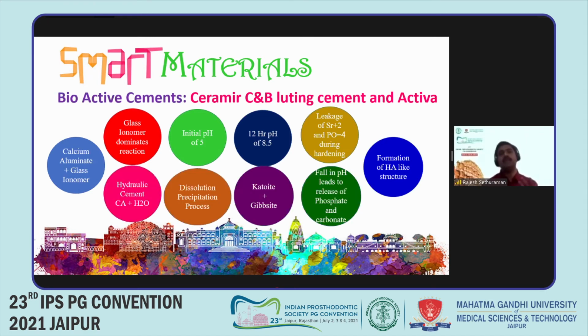On the other hand, we have the calcium aluminate, which is already present in it, which reacts with water and forms a dissolution and precipitation reaction, which ultimately results in two components, katoite and gibbsite. Both of them result in a rise in the pH, so the pH becomes as high as possible. Whenever there is a fall in the pH, that is, whenever there is an acid attack and the critical level of 5.5 is breached, there is release of phosphate and carbonate, which together with the leakage of strontium and phosphate from the glass ionomer component results in the formation of a hydroxyapatite-like crystal. Believe me, Ceramir C&B and Activa result in post-operative sensitivity of negligibly zero.